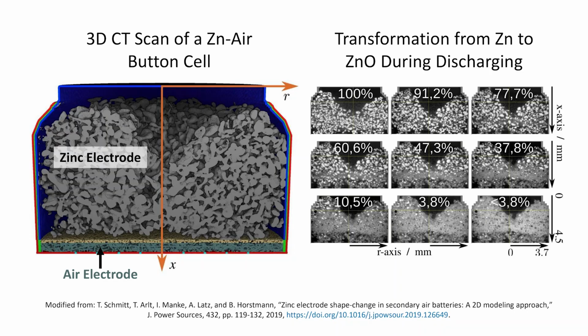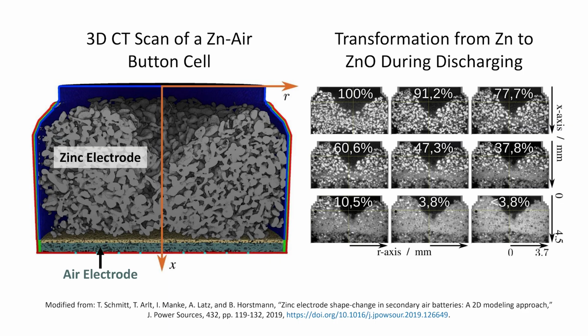And one of the interesting things and one of the challenges in zinc-air batteries is that when your zinc electrode is discharging, it's dissolving from metallic zinc to aqueous zinc species, and eventually it hits a saturation limit where it starts to precipitate out zinc oxide, which is your final discharge product. And that might be okay, except for two things. Number one, zinc oxide is about 60% bigger than zinc. So that means that as the cell discharges, its volume is going to want to expand. The second problem is that zinc oxide tends to precipitate onto those zinc surfaces where the reaction is taking place.